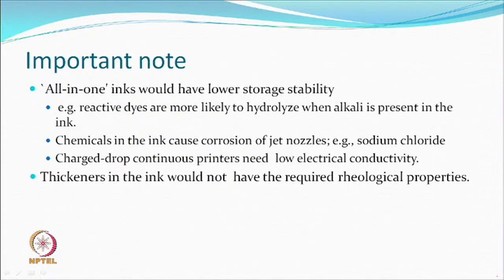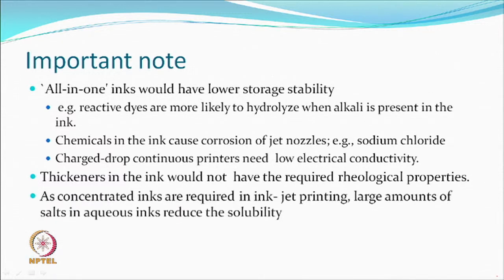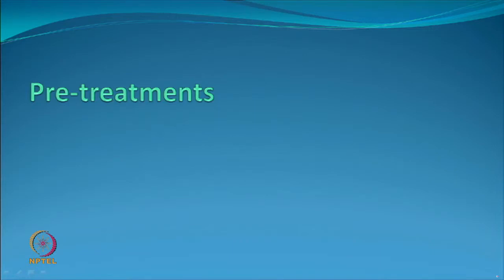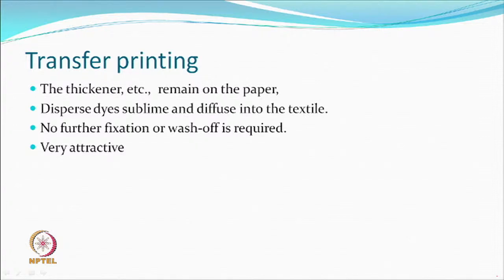Thickeners in the ink may not have the required rheology because low viscosity is required. If you require some way to control diffusion, it is not a good idea to have such thickeners very easily in the ink — rheological properties will be affected. As mentioned earlier, inks will be highly concentrated solutions or suspensions of the dye or pigment. If salts are present, other than corrosion, they reduce the solubility of the dye, particularly in aqueous systems. So all-in-one cannot be considered a good idea, and so we work on what is called pre-treatment.